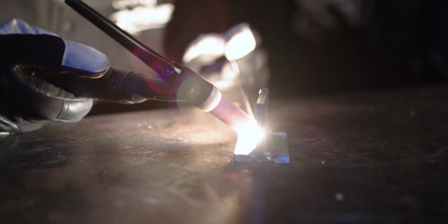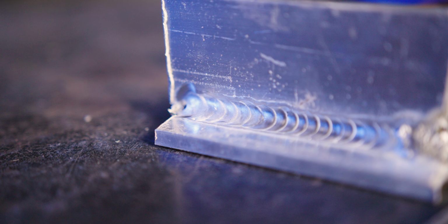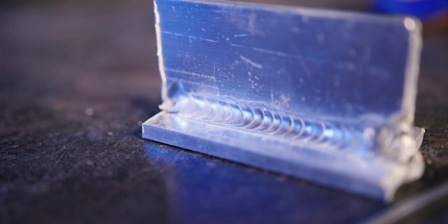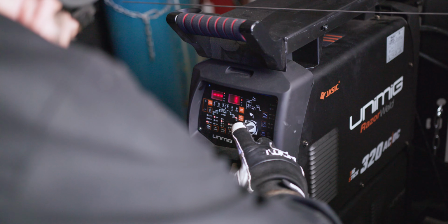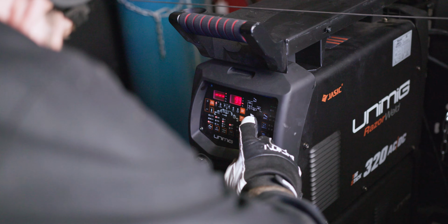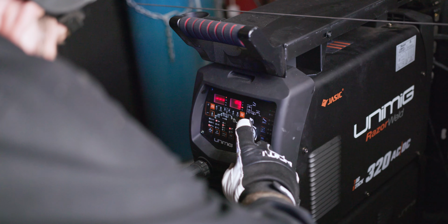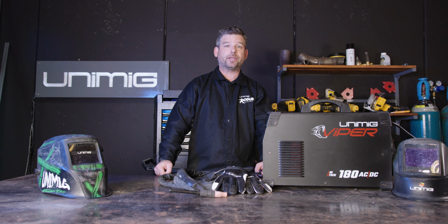The operator can select a percentage of AC and DC minus during a full period, which can be varied from 5 to 95%, though it's a good idea to have more than 50% DC minus. This feature is pretty specialised and is meant for advanced welders. Our Razor 320 AC/DC is the only welder at the moment that carries these capabilities.